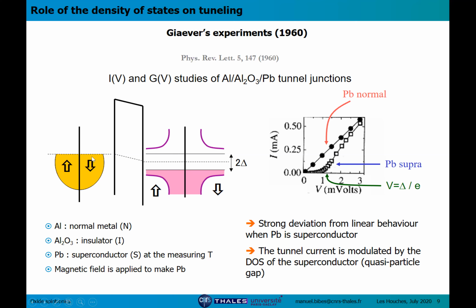So in principle, when you send electrons from a normal metal, shown here, across the barrier to the lead, if the energy of the electrons, which is set by the bias voltage that you apply between the two electrodes, is very small, they may arrive in the gap, and so they cannot tunnel because there are no states for them to tunnel into. So in this case, there will be no current, and only when the voltage is high enough so that the electrons can tunnel into the density of states of the lead above the gap, where there are states available, will the current start to be finite.